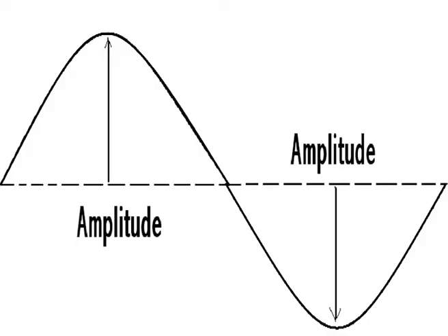This interactive process results in the interference of tension waves if they are coincidentally in phase. The amplitude of the waves will be additive, and as a result of the accumulation of tensile stress, it results in the fracture of glass. Thus, a flake of glass is ejected from the opposite side.